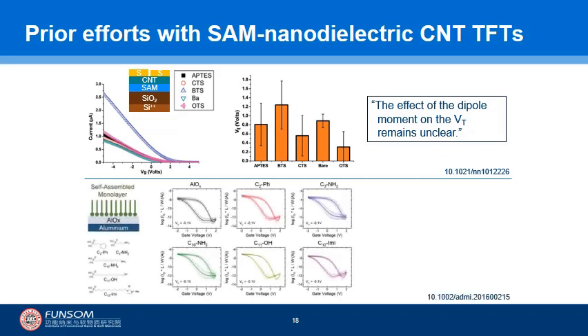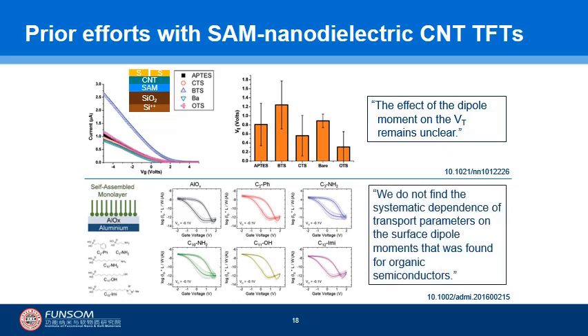The only other relevant work is from the Zaumseil group. In this study, they tested a number of hybrid nanodielectrics comprising different SAM molecules. Also in this case, the resulting transistors were p-channel only, and additionally presented very large hysteresis, as you can see from these plots. In fact, such hysteresis prevented any assessment of the trend in threshold voltage shift versus dipole moment of the SAMs. All of this indicates that the controlled shift we have achieved with our ambipolar CNT-TFTs and our ability to directly link it to the SAM dipole moments is a first for CNT-TFTs.